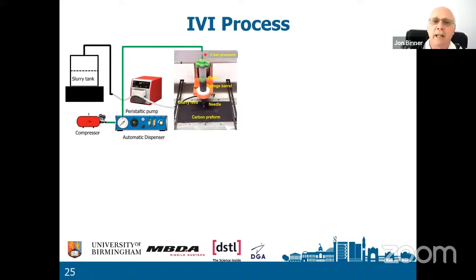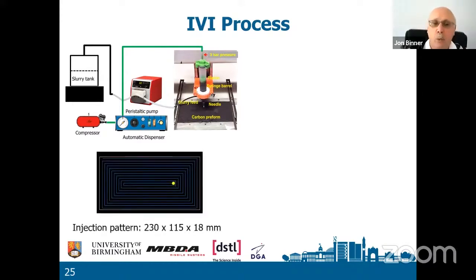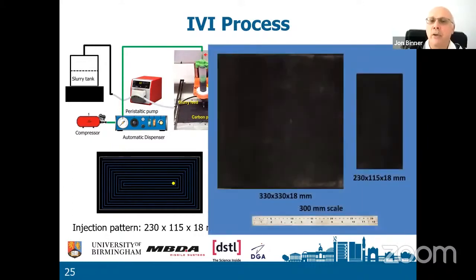So we've got there an XY plotter. It moves the needle and the syringe about, and then you apply the pressure with a peristaltic pump, and you squeeze down and you deposit an exact amount of slurry exactly where you want to put it in the preform. And so we learned that you apply an approach like this, where you start at the middle, you deposit at the middle, and then you work your way towards the outside. And there you can see the injection pattern for one sample. And then here you've got some samples. You can see the dimensions.